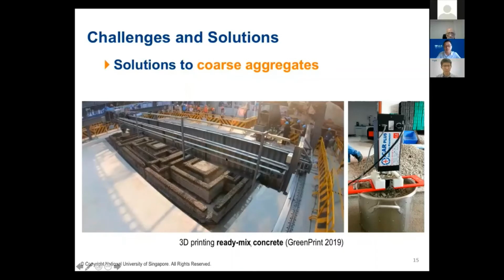From the figure on the right, you can see that they can include coarse aggregate in the mixtures of the concrete, and then they put it into the printer head, and then they can print a power station. You can see the dimension is quite huge. But one thing I need to highlight here is that if you observe carefully, I circle it to highlight that in this printer, they don't have the pumping. So they discharge the concrete and then directly put the concrete into the printer head. Then they can print it, the fresh concrete. That is the key thing why they can 3D print the ready-mix concrete. Otherwise, if the 3D printing is connected with the pumping, it's very hard.